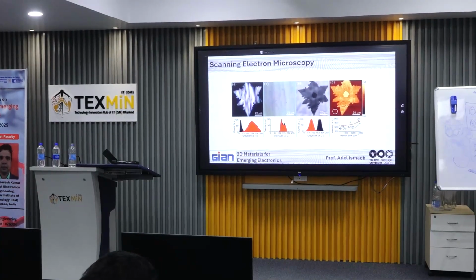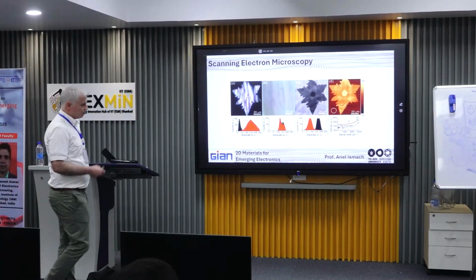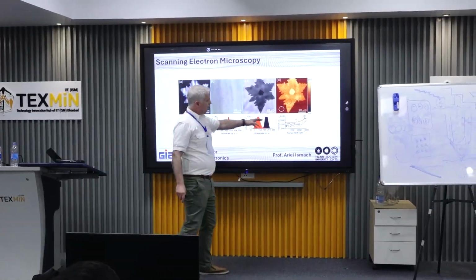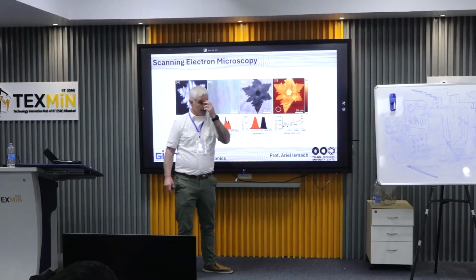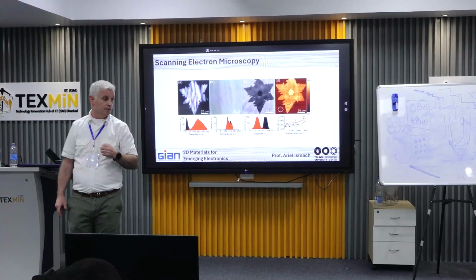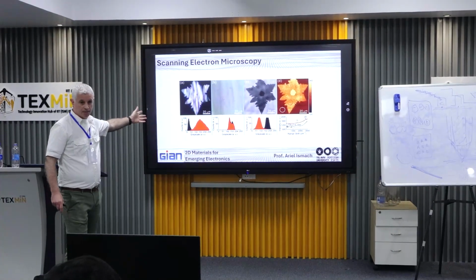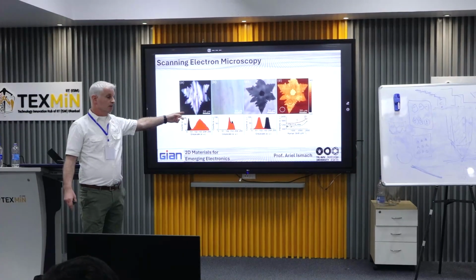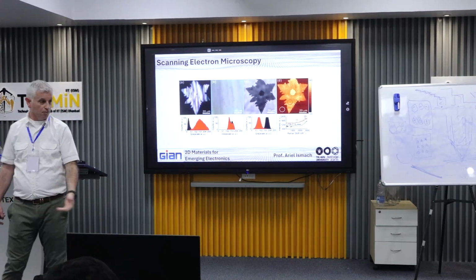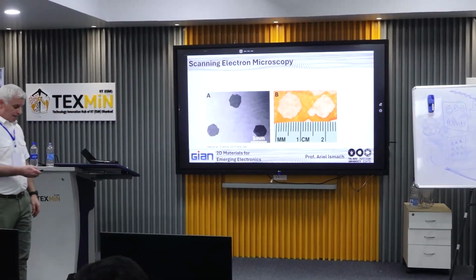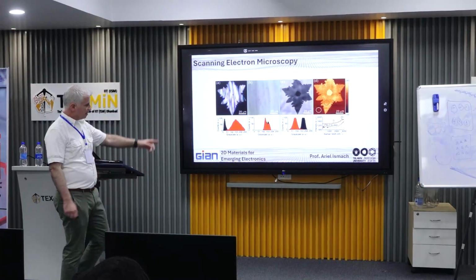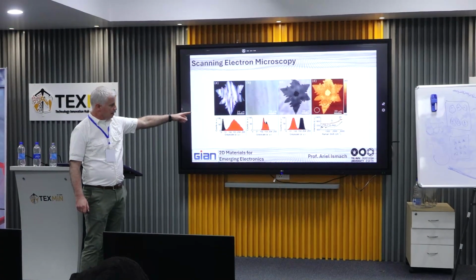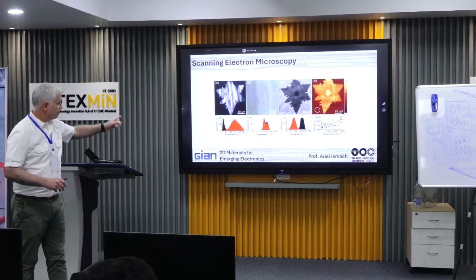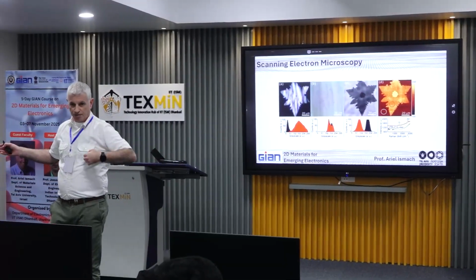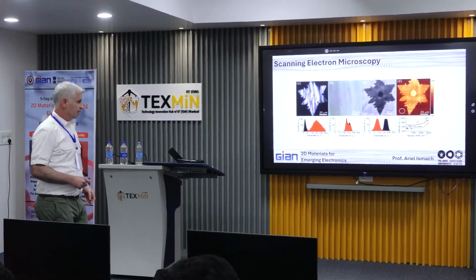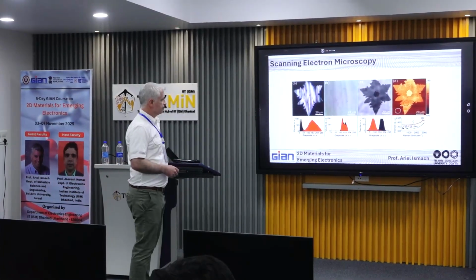But the disadvantage of the Raman is that scanning tens of microns takes quite a lot of time, right? While this takes 2 minutes, and this, well, it depends how long you wait for the spot. But if you have a spot now, it will take you an hour. And another big difference is that because of the time consumption, the Raman mapping is good for relatively small areas, while the other two methods are very good for very large areas. Okay, so you always need to combine the methods in order to address all these issues.